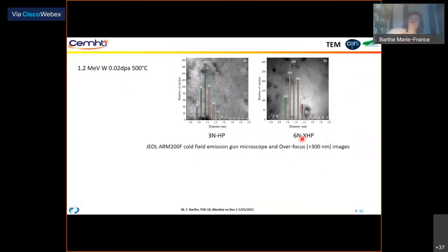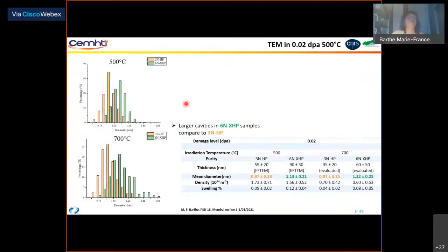And then we also performed TEM on these samples, and you can see some typical images for both purities for irradiation conditions at 500 degrees C. The cavity distribution has been plotted here for the different types of sample, in orange the 3N and in green the 6N, at both temperatures, and it is clear that the vacancy clusters or cavities are larger in the 6N sample. Here you can find the mean diameter and the density, which is 10 to the 23 per cubic meter, sorry.